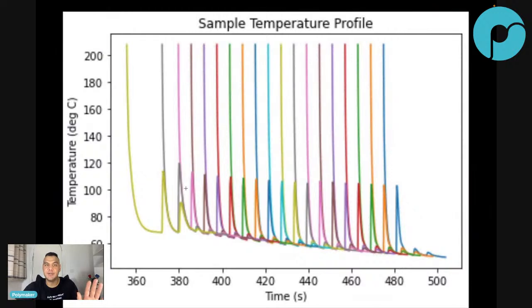Do you remember the chart here? Do you remember this? Every time there is a layer printing on top, it is going to reheat the layer below it. And sometimes it goes above Tg, so it's going to relax even more. It's like it's relaxing and then frozen, and then reheating, so it relaxes again and then frozen, then reheating a little bit and then relaxes more. Does that make sense? So if you print fast, the temperature doesn't have time to diffuse. So with the same parameters, the same everything, printing fast or printing slow, I think printing fast is worse. I'm still thinking about it because maybe I'm missing something, but yeah.